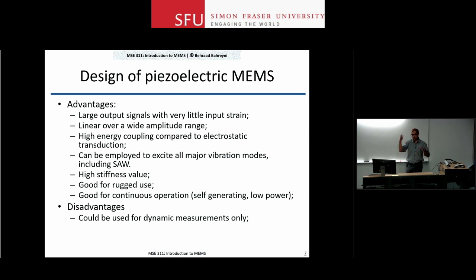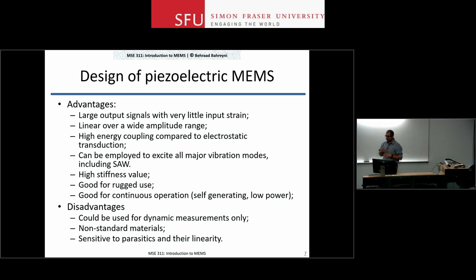For AC sensing, if instead of a DC acceleration you want to measure vibrations, that's an excellent choice. The materials for piezoelectric transduction are not standard microfabrication materials. As I said, there is a growing number of foundries that provide access to these materials, but still relatively niche. And the issue that you will have with piezoelectric transduction is that you have to actually know more about your parasitics. Because the method itself, the transduction itself, is fairly linear, but the parasitics that you may have around may not be linear. So you may see some nonlinearity in the operation, which comes from the parasitics and not the device itself.